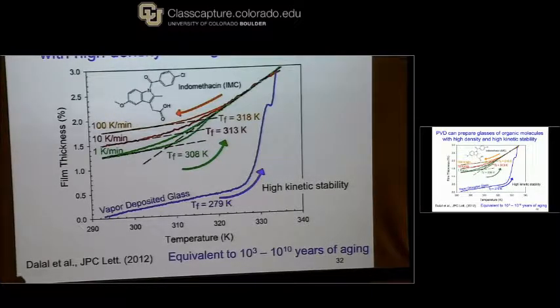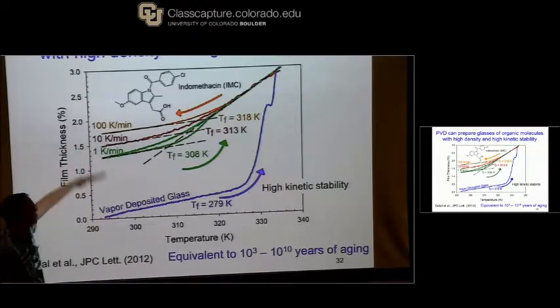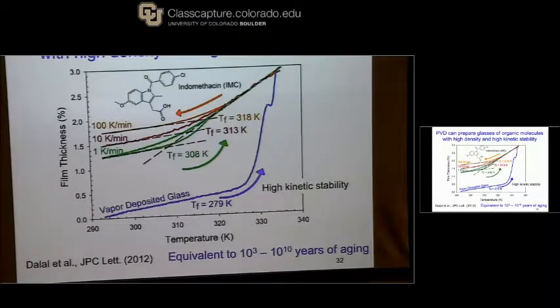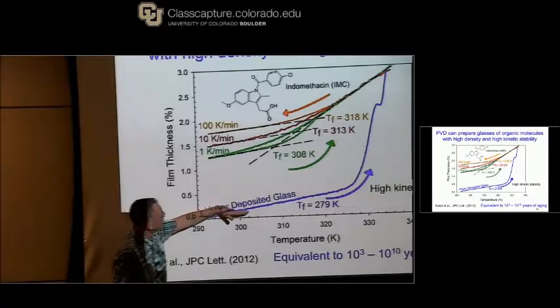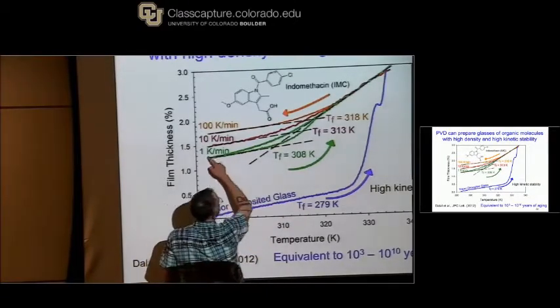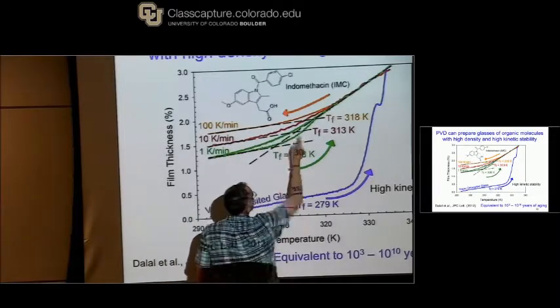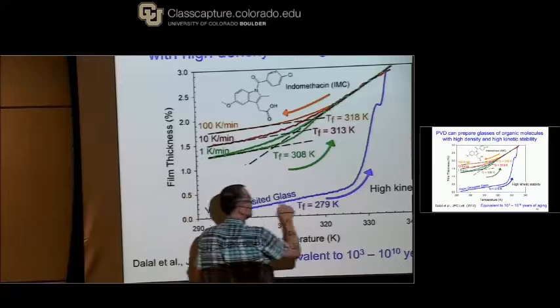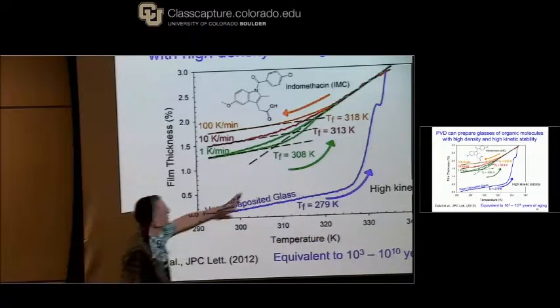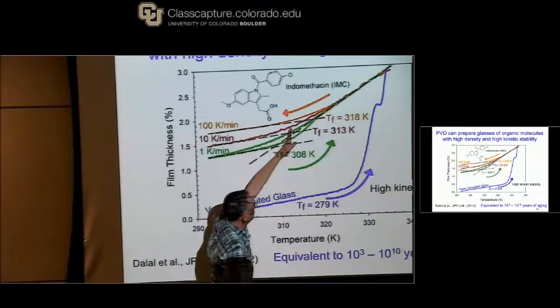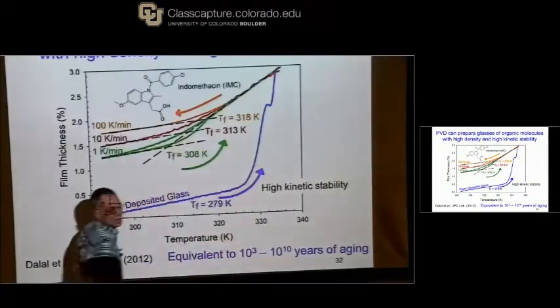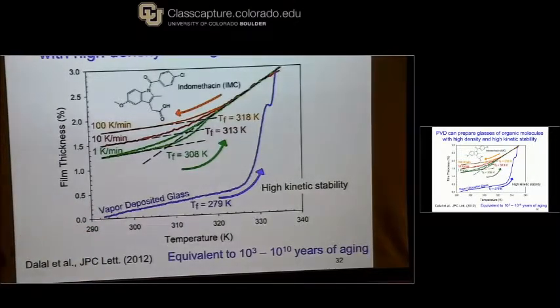Okay. So it's interesting that the vapor deposited film starts down here. So it's thinner by about 1.5%. More dense. That's one interesting thing. The other interesting thing is that when you heat it up, let's compare to this. This is heating at 1 Kelvin per minute for a liquid cooled glass. This is heating at 1 Kelvin per minute for a vapor deposited glass. You see, this material is starting to turn into a liquid here. This material doesn't turn into a liquid until I go up another 20 Kelvin or so. So that's an indication of kinetic stability. And this is a measure of density.